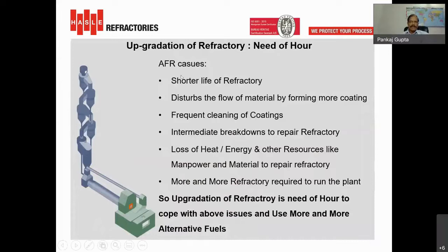So what happens? AFR causes a shorter life of refractory and disturbs the flow of material by forming more coating. Frequent cleaning of coating is required. Intermediate breakdowns are needed to repair the refractory if it fails before the campaign life. There is loss of heat and energy and other resources like manpower and material when you repair that refractory. And to run the plant for a full campaign, more and more refractories are required. Even when the plant is taking a shutdown, more and more refractories are required to repair, to run the plant again.